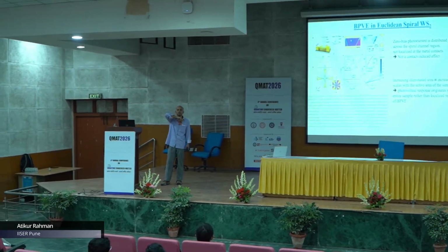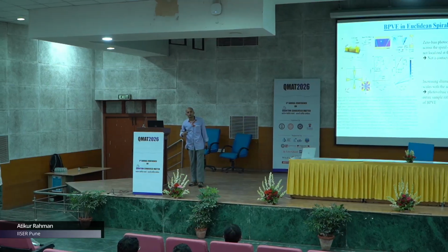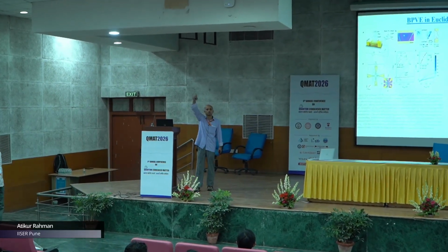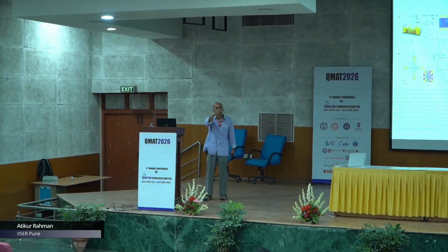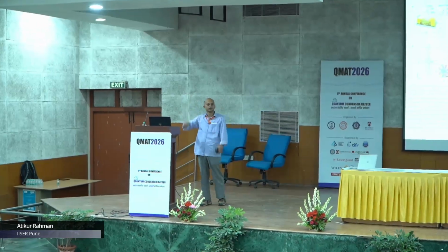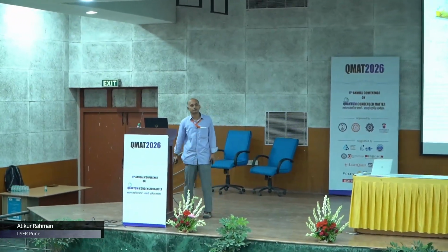Fill factor in bulk photovoltaic systems is generally pretty low, because you see the triangle, not a rectangular kind of thing. If it goes more towards a perfect rectangle, then you get a very high fill factor. But in this case, you'll never get that.